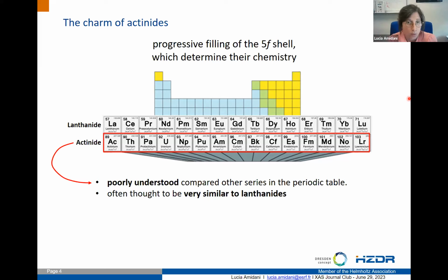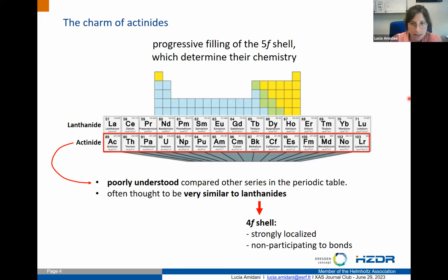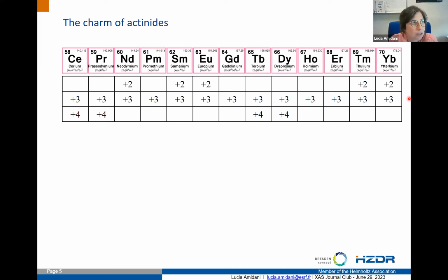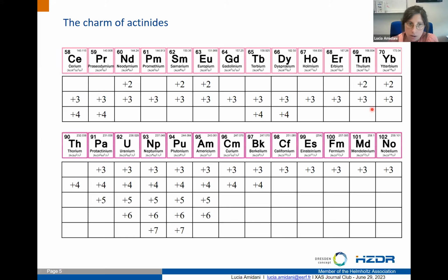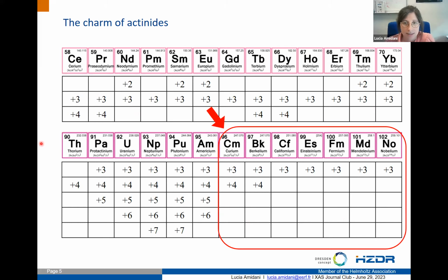Indeed, this was also what I thought before joining Grenoble and having a look myself. The lanthanides are characterized by the 4f shell, which is well known to be very strongly localized and generally not participating strongly in bonds. So we can have a look to see if this is really the case for the actinides as well. Here we are with the oxidation states of the lanthanides, which are dominated by the 3+, as you see here, with few exceptions. If we go to the actinides, the table becomes much richer. We have a full first half of the series where numerous stable oxidation states are found, while the second half is more similar to what the lanthanides show.